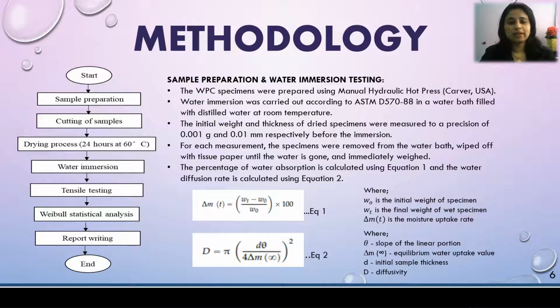The initial weight and thickness of the dried specimens were measured to a precision of 0.001 gram and 0.01 millimeter respectively before the immersion. For each measurement, the specimens were removed from the water bath, wiped off with tissue paper until the water is gone, and immediately weighed. Lastly, the percentage of water absorption rate is calculated using equation 1, where the final weight of specimen minus the initial weight is divided by the initial weight and multiplied by 100%.